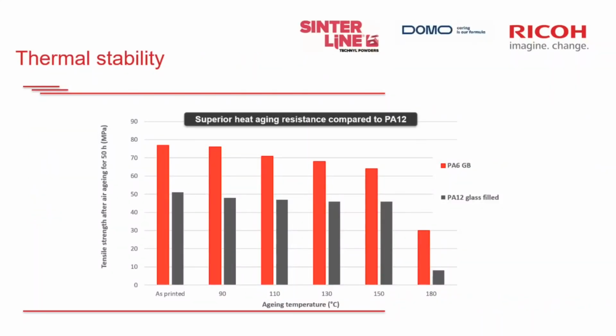So to illustrate some of the properties of this material, if we compare, for example, the tensile strength of nylon 6 glass beads against a glass-filled PA12, nylon 12, we can see that the value for nylon 6 glass beads is far greater than the one for nylon 12 glass beads. And also, as we can see on the graph, nylon 6 glass beads demonstrate better retention of the mechanical properties as a function of temperature, and in particular at high temperature. In this specific case, the parts have been tested for aging in air at different temperatures during 50 hours.